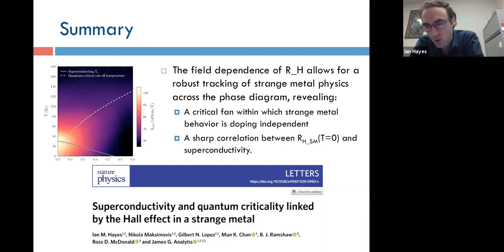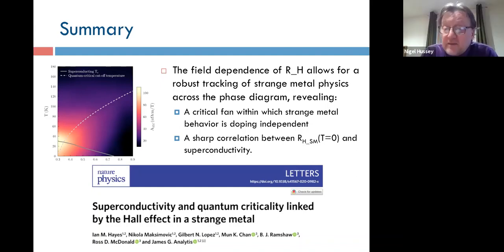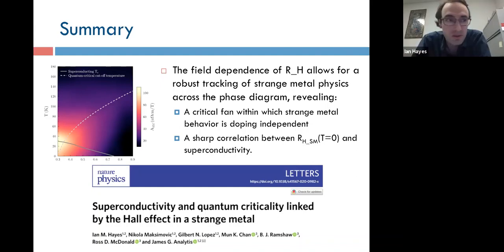So I think qualitatively it can produce an enhancement of the Hall coefficient with anisotropic scattering generically. It has a similar effect to having two sheets. Yeah, but specifically the field dependence. Oh, specifically the field dependence. I think generically you do expect whatever increase in RH you get from anisotropic scattering to decrease with field. So that way it is actually consistent.